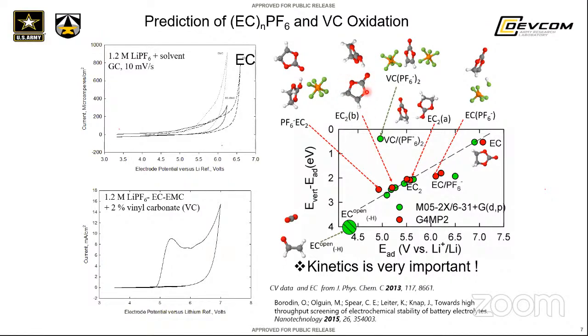All right. Unless, that's actually a very good point, depending on the environment, this radical can undergo second reduction. Exactly. But then a second electron gets transferred. So the first one is a proton and neutral radical, and if it sticks around, then the radical becomes a cation. But if the radical floats away as neutral, it releases CO2, and then the other part, the open part, gets oxidized and becomes active in attacking other solvents. I see. Okay. Thank you.